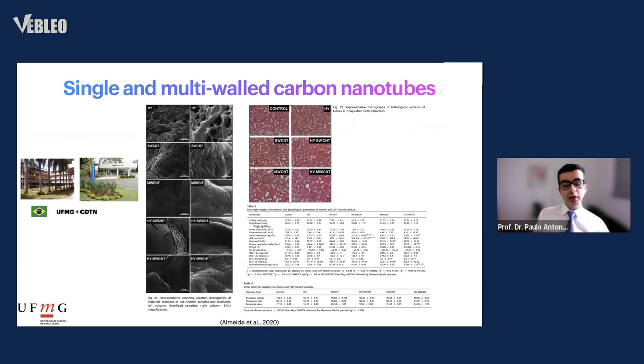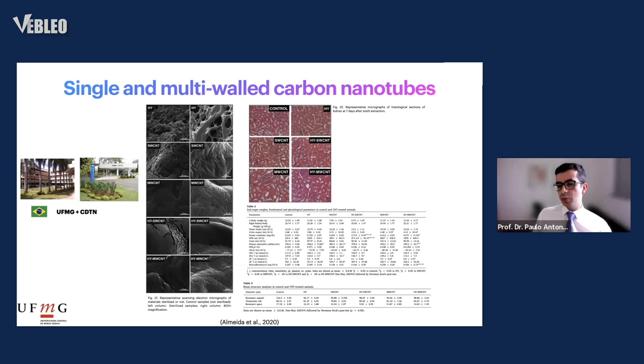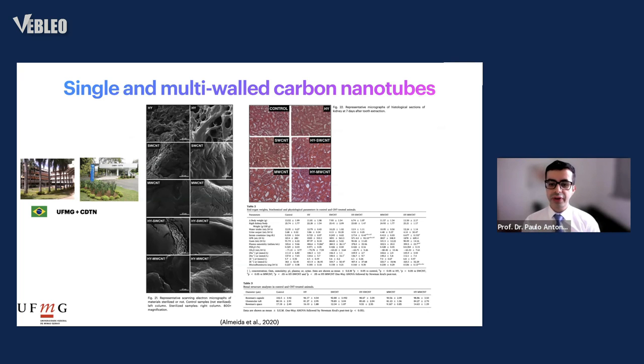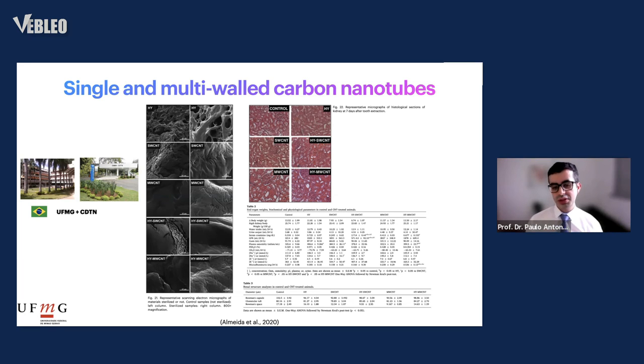Recently, we conducted another experiment with single-walled and multi-walled carbon nanotubes to investigate the effects of sterilization on these materials. In figure 21, scanning electron micrographs show that sterilization has no detrimental effects on the surface of these materials. We also investigated the effects on kidney function and did not see detrimental effects of these materials on the kidney of rats. Tables two and three show that the parameters of this organ were not compromised by carbon nanotubes, functionalized or not with hyaluronic acid.